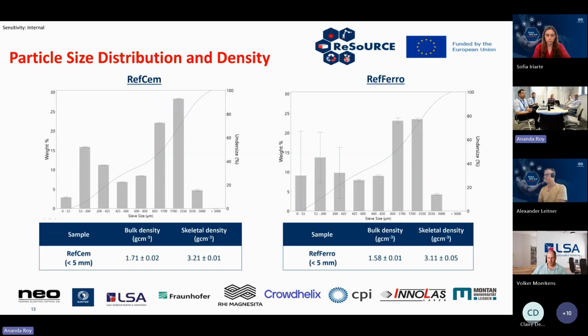We then had a look at the particle size distribution and the density of these materials. So although they are a 0 to 5 millimeter size fraction, we didn't know how the particle size distribution would vary across that range. And we actually see that both of these materials have a bimodal size distribution with size classes dominant at around 53 to 200 microns and 1700 to 3,500 microns. The bulk density of both materials is fairly similar, 1.7 for the RefCem material and 1.6 for the RefFerro material. And the skeletal densities are then 3.2 for the RefCem material and 3.1 for the RefFerro material. The difference between the bulk density and the skeletal density is due to the voids that are present when you measure the bulk density.